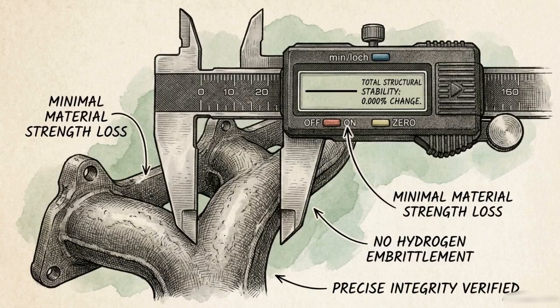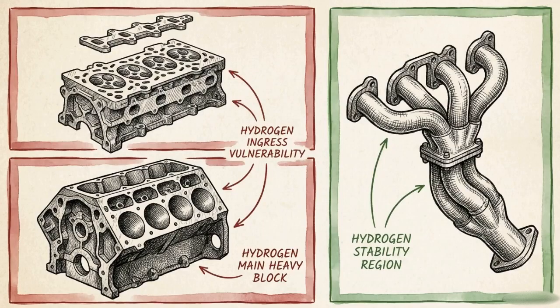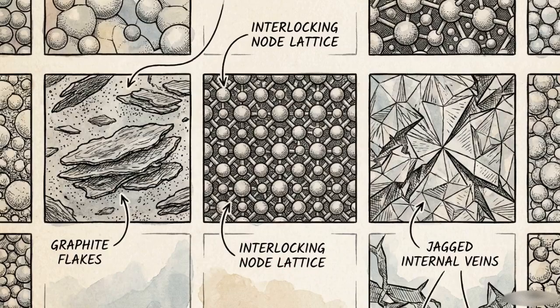The testing produced an anomaly. The ductile cast iron exhaust manifold showed minimal strength loss, proving microstructural morphology redefines an alloy's resistance to failure. Material failure in a hydrogen combustion engine is not universal. It is strictly dictated by the microscopic trap site distribution of the specific alloy chosen for the part.